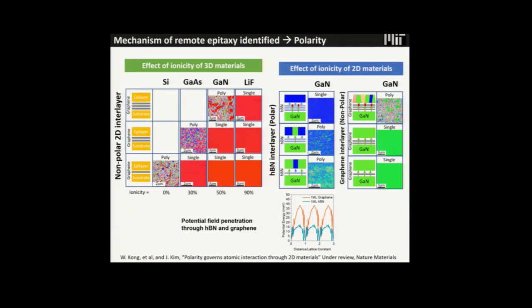There is no remote epitaxy through graphene from the silicon substrate. Also, we're kind of shocked. Why is poly? Why there's no remote epitaxy? Then we try to find out the critical graphene thickness, interlayer thickness, to secure the remote epitaxy. So here, we succeeded to do the single crystalline through monolayer graphene for gallium arsenide. Then if you increase the layer, two monolayer of graphene, you get the poly. Oh, there's certain correlation.